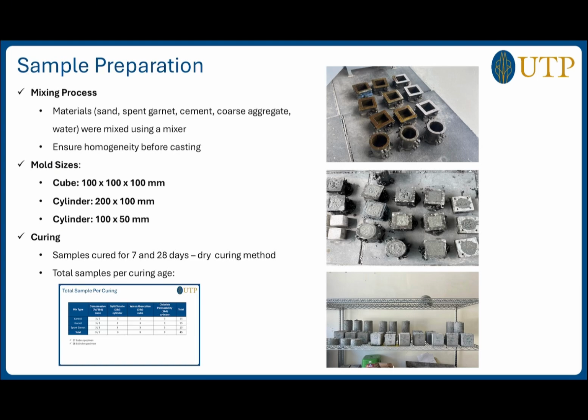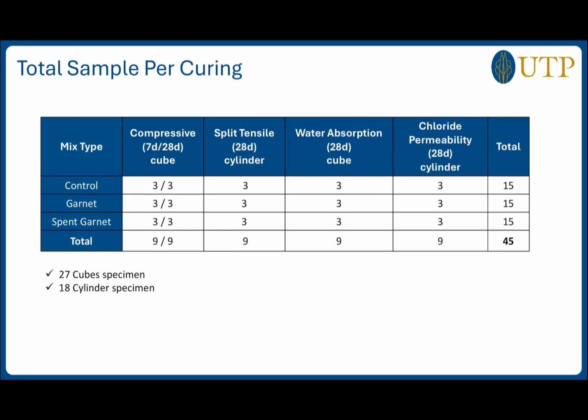mixer, and these are the mold sizes that I use, which is cube, cylinder 200 x 100, and cylinder 100 x 50. And for curing process, all the samples are cured for 7 and 28 days, and they undergo a dry curing method because we don't want any leaching of spent garnet or garnet during that process. And total sample, we have 45 samples, 27 cubes and 18 cylinders.